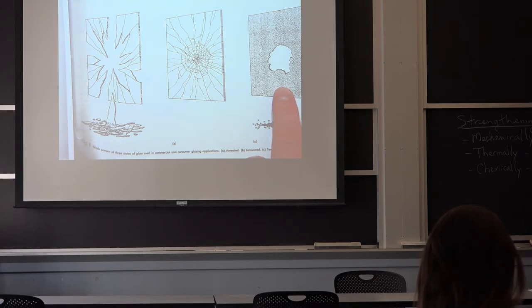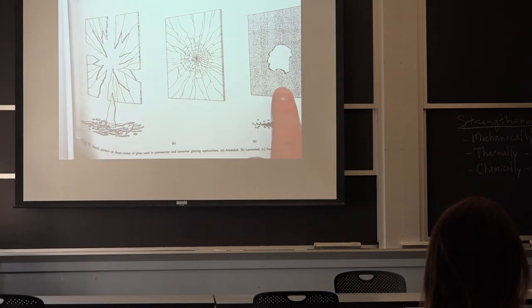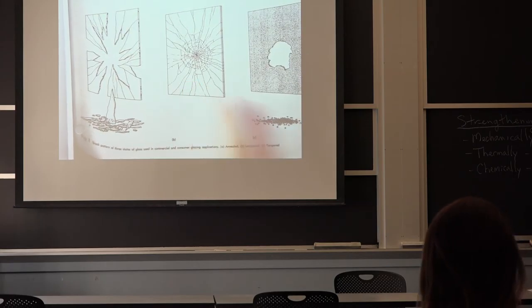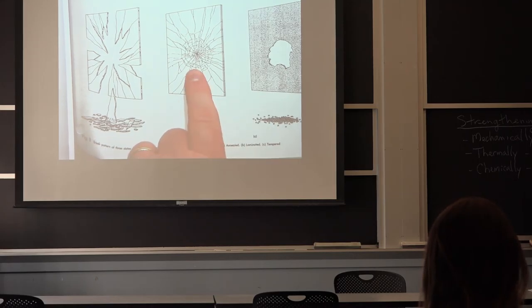Side windows are not laminated, but a side window, sometimes it'll have a little scratch in it that's a little deeper. A stone hits the side window and makes a deeper scratch, and you have cold weather, and you come out and you find you've got little pieces of glass. The whole window shattered, the tempered glass along the side windows. You put laminated glass in the front windshield because if you take a rock in the front, you want it to kind of hold together.